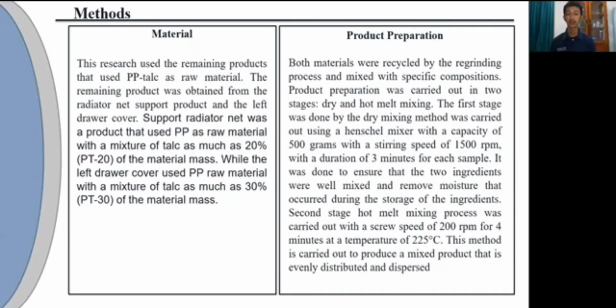Second step, the hot melt mixing process was carried out with a screw speed of 200 rpm for 4 minutes at a temperature of 225 degrees Celsius. This method is carried out to produce a mixed product that is evenly distributed and dispersed.